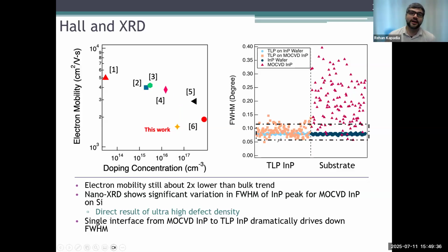And so one of the cool measurements that has been done on this is nano XRD. So essentially we take a nanoscale X-ray beam and we use that to very locally probe the properties of the material. And what we can do from there is look at the full width half maximum of the reflected beam due to our crystal lattices. Essentially, if you have a perfect crystal lattice, then when you have a reflection in an X-ray system, that will have 0 width. And because you have imperfections and strain and defects, and defects cause strain, that will broaden out those peaks. So essentially, the wider the peak, the worse the quality. This is just a heuristic that you can use here. I wouldn't say that's exactly true, but that's about what's true.